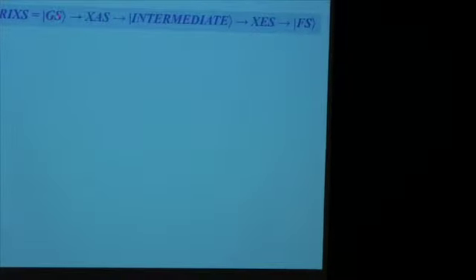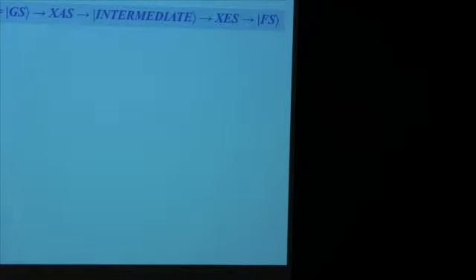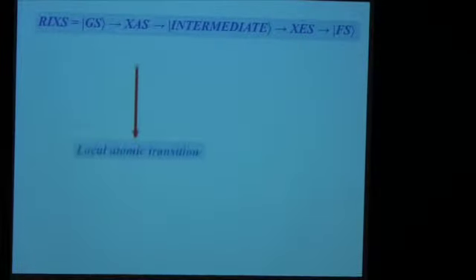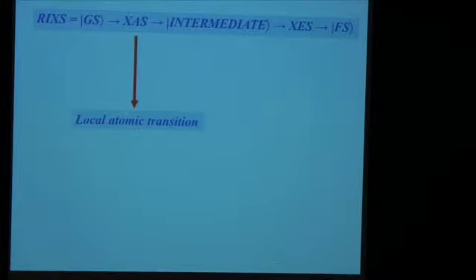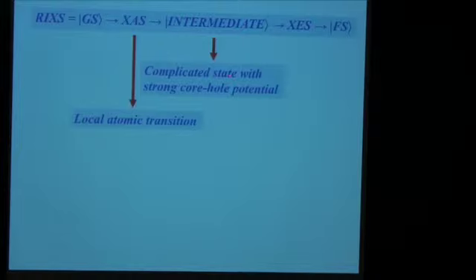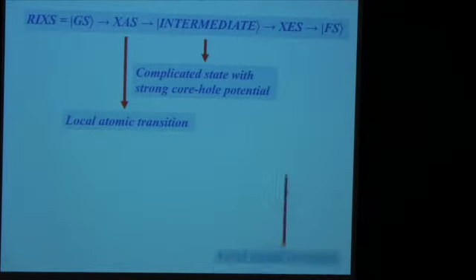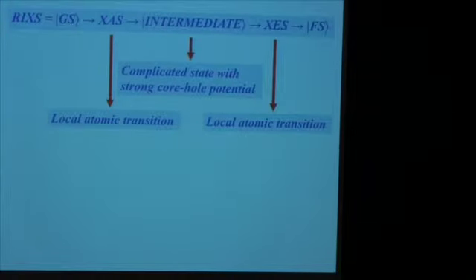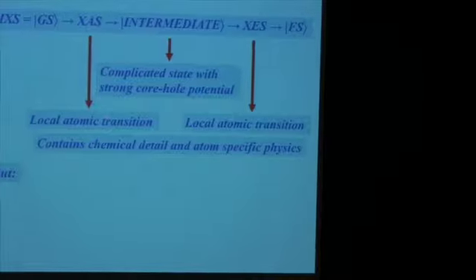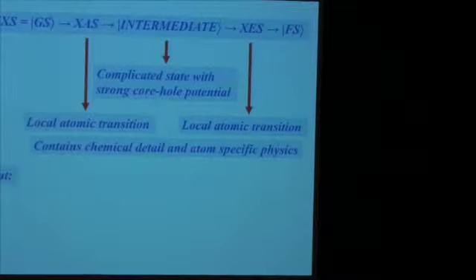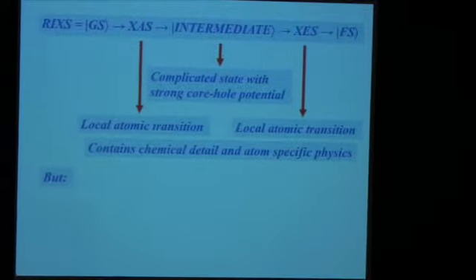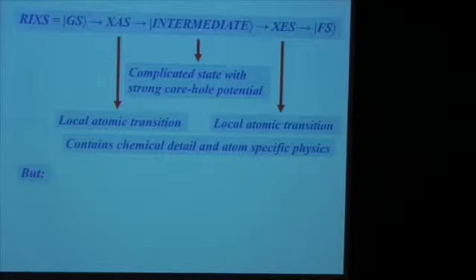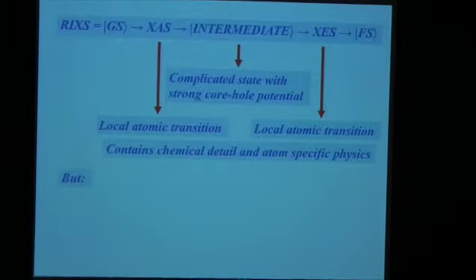Because it's, well, I have a ground state, I do X-ray absorption. In X-ray absorption, I have a core hole, I shake up all my electrons, I come into an intermediate state that's complicated, then in this complicated intermediate state, I do X-ray emission, and I end up in the final state. I have a local atomic transition, X-ray absorption, and a complicated state with a strong core hole potential in the middle, and then again I do a local atomic transition. So the local atomic transitions, of course, contain all chemical detail and are completely atomic specific. So now you have a problem that's very specific and complicated. So that's not a problem you want to have, right?